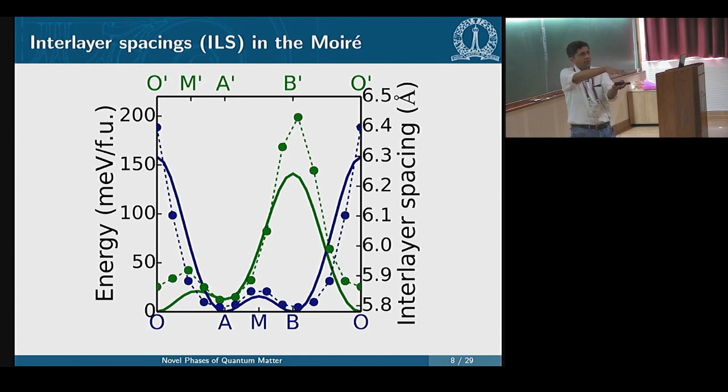When I rotate two layers with respect to the other, and I let the system relax, because the stackings are different, and different stackings have different equilibrium spacings, the sheets bend. Question is by how much? You can see the scale on this side is the separation between the moly to moly distance. It can vary quite a lot, half an angstrom or more. So these sheets are actually not flat. These sheets are bent.